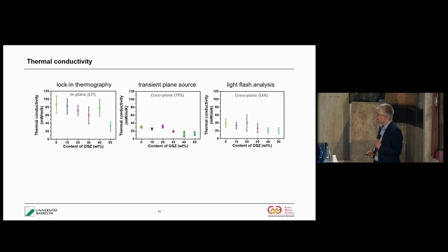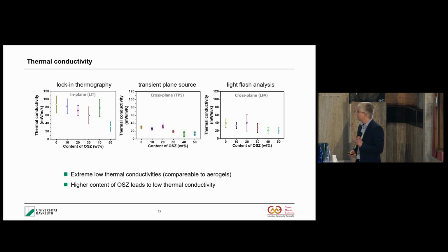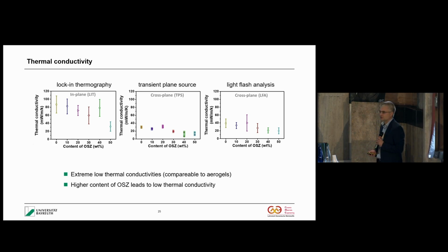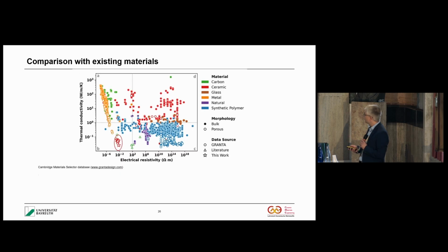The other aspect is that these fibers have a low thermal conductivity, which was very interesting. So we wanted to investigate not only the electrical conductivity, but also the thermal conductivity. But then we observed that their thermal conductivity is extremely low. So that's actually comparable to aerogels, which we found out. So that means it has a very low thermal conductivity, and a higher content of the organosiloxanes actually leads to a lower thermal conductivity, which is also interesting. So that means the amount of the siloxanes plays a big role.